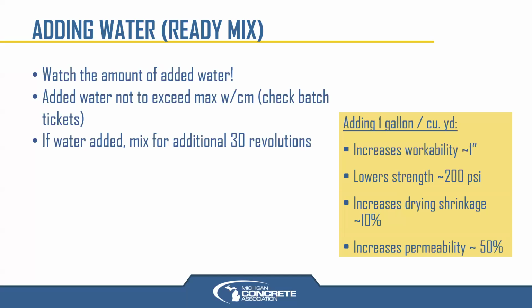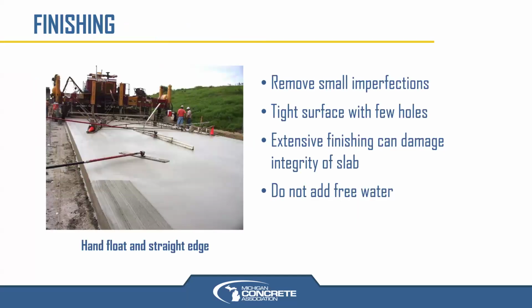And then a big thing, especially if it's only added to the surface, finishers need to watch this. It increases the permeability up to 50% by adding that 1 gallon per yard. And that's mixed in. If they add to the surface, it's directly just on the surface that is more permeable then. So watch that addition of water to concrete. We need water, but we only need a certain amount.